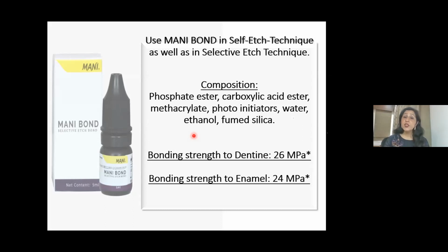With this, bonding strength to dentine is 26 MPa, which is great, and to enamel is 24 MPa. This is with selective etch, my dear friends. And if you use total etch, I'm sorry, when you use only self etch, then the bonding to dentine and the enamel even goes higher. So with self etch, the dentine bonding strength is 26, with enamel is 24. And when you use selective etch, when you etch the enamel with phosphoric acid gel, then the bonding strength to enamel will go higher. On dentine, it will remain the same.